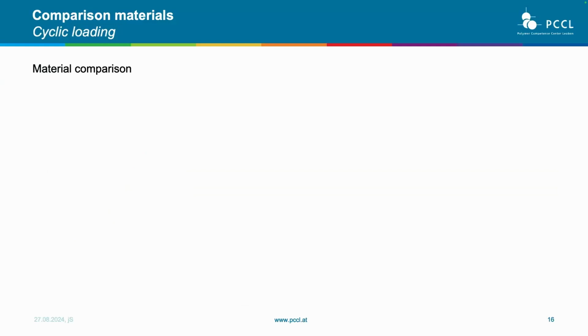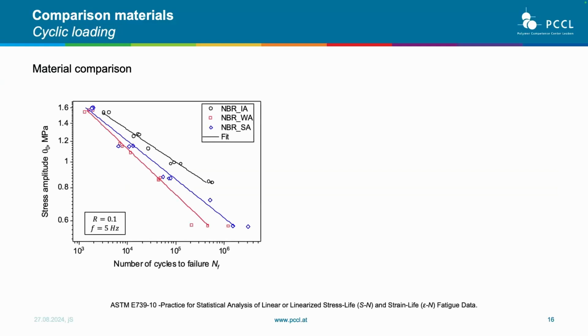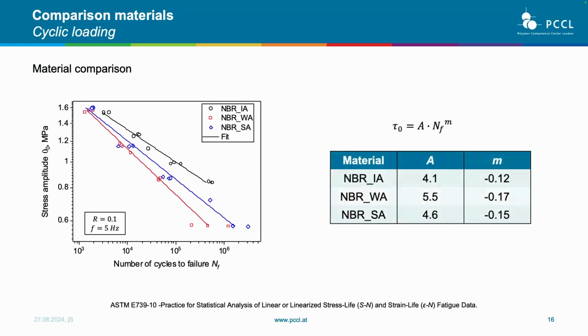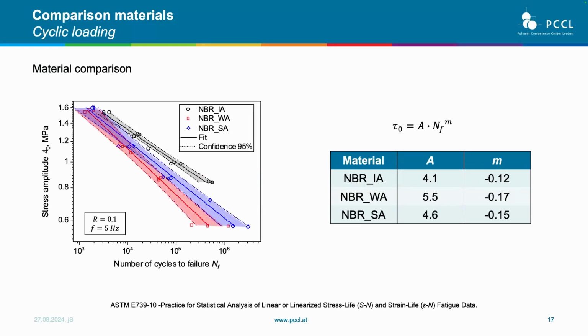Major differences can be found when we deal with cyclic loading. In cyclic loading, we clearly see 3 different lines. Of course, when we move to the right, we have a better resistance to failure, so a better adhesion. And this is also testified by fitting with the power law according to this standard. And also by considering the confidence interval of 95%, it's clear that we can even distinguish between the water base and the solvent base.